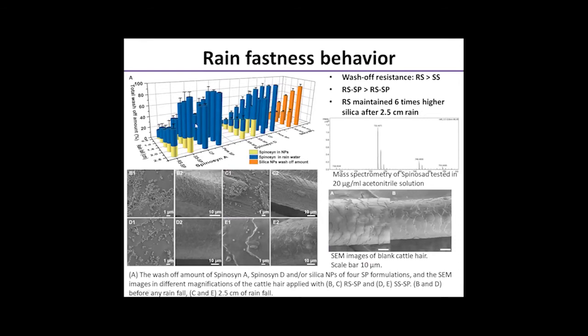As shown in figure A, the wash-off amount of silica nanoparticle carriers is shown in the orange bars. The wash-off amount of rough silica nanoparticles is much lower than that of smooth silica nanoparticles at all rainfall strengths from 0.5 to 2.5 centimeters. At the highest rainfall of 2.5 centimeters, it is calculated that 6 times more rough silica residue remained on the cattle hair than the smooth one, proving that the rough surface topography of nanospinosad can greatly enhance their cattle hair adhesive capacity and the rain fastness property.